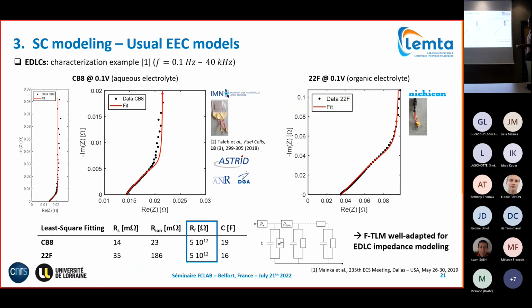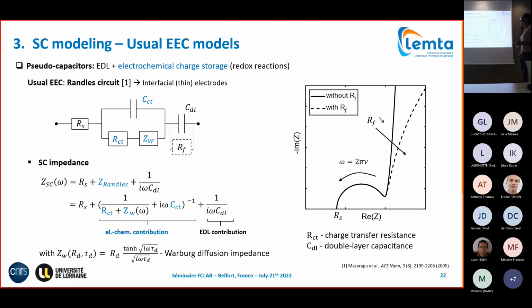And you see that as we have a vertical line, lower frequencies means very low, or the absence of, self-discharge, which corresponds to a very high leakage resistance. So that as well is in agreement with our expectation. This proves the validity of our fractional TLM for our devices. Okay, that's the case of EDLCs.